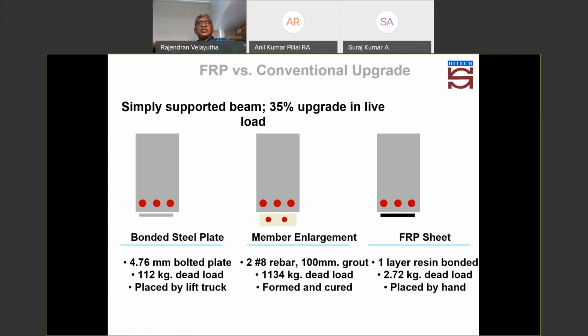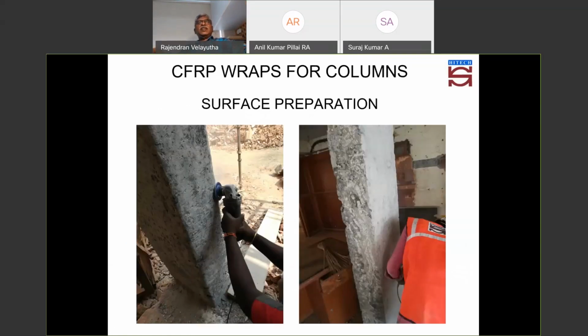If it is not possible, then shift to either of the other two systems, which are available and have a proven track record. But of course, one disadvantage of FRP is that it always goes with an epoxy glue as an adhesive, and so you have a fire issue. You can address that very well also. We grind the surface to make it very fine. After the grinding, you can see that epoxy putty has been applied, so we have a pure system.